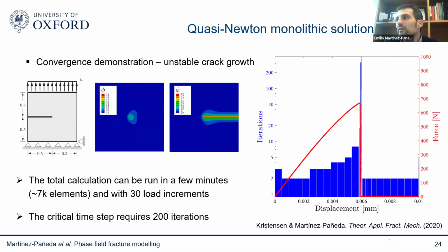So this is what you see here on the right. Look first at the red curve. This is the force versus displacement curve. You can see that initially everything is linear, then eventually a little bit of nonlinearity due to the damage, and at some point, this unstable crack growth event happens, and you lose all the load carrying capacity, and you end up here. And you can imagine how challenging it is from a computational perspective when you use a Newton method to jump from here to here, right? You're looking for a solution somewhere near here, but your real solution is actually down there because your crack propagated suddenly and you lost all your load carrying capacity.